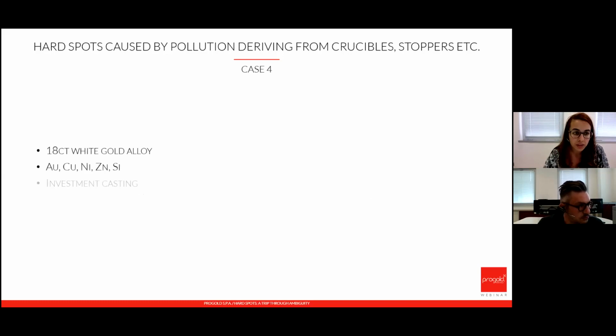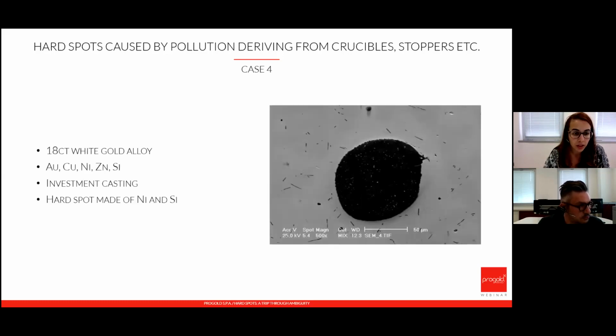Here, as you can see, we have a nickel alloy containing nickel and silicon. The hard spot that you're seeing is very round, very perfect. Why does this happen? Nickel and silicon are two elements that are very common together. However, there are some metallurgical ratios that we have to keep in mind while using them together inside the alloy, because if we don't respect them, we might have problems.